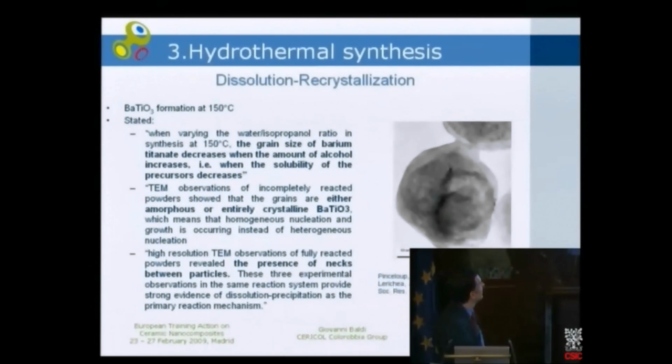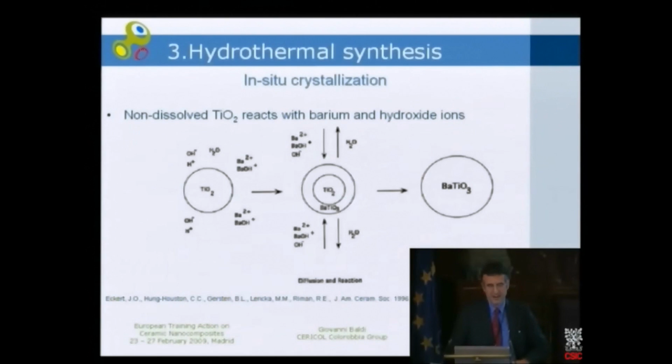This is a hypothesis. High resolution TEM observation of fully reacted powders reveals the presence of necks between particles. These three experimental observations in the same reaction system provide strong evidence of dissolution precipitation as the primary reaction mechanism. In fact, another proposed mechanism is in situ crystallization, in which non-dissolved titanium oxide reacts with barium and hydroxide ions. This was proposed by Ebert in 1996.